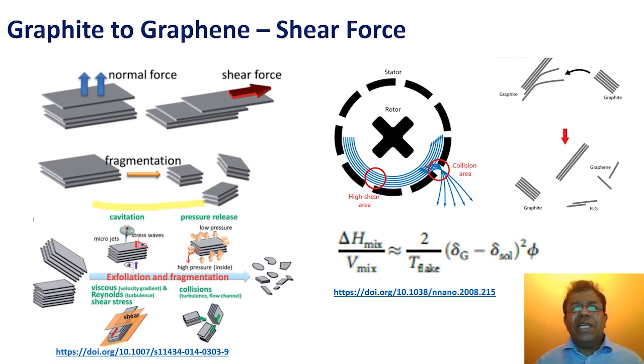The fragmentation effect has double-edged tactics. On the one hand, it can reduce the lateral size of graphene. This is not desirable for achieving large-area graphene. On the other hand, it facilitates exfoliation because smaller graphite flakes are easier to exfoliate than larger ones, because of the smaller collective van der Waals interaction forces between the layers in smaller graphite flakes.